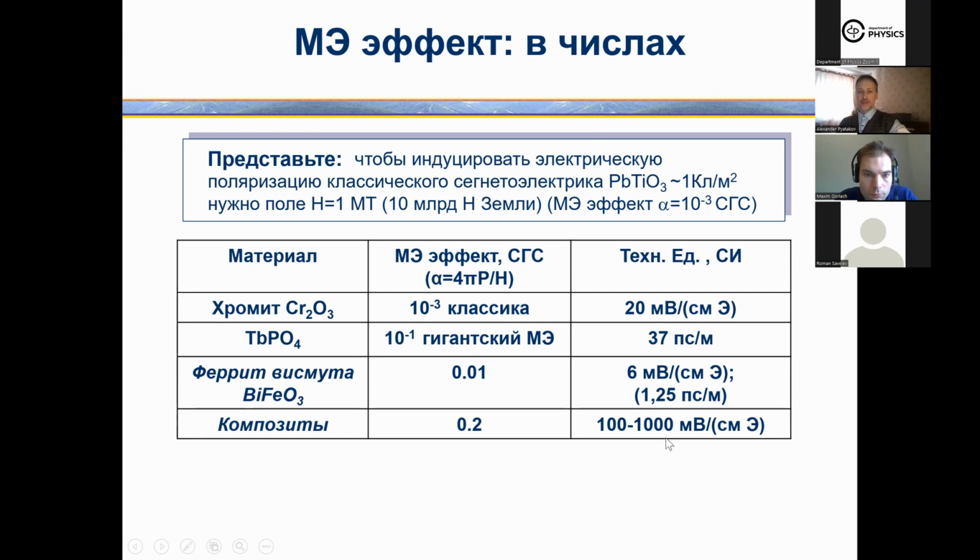And in the case of composite, and in the case of resonance, you can vibrate it, and due to the proper frequency, when you apply a frequency close to the proper frequency of the structure, there's a kind of resonance, and you can obtain up to volts or even tens of volts when you apply an Ørsted field. Right. Thank you.